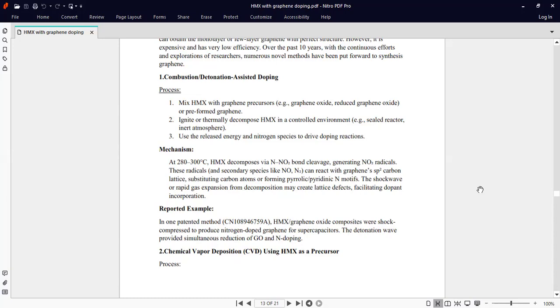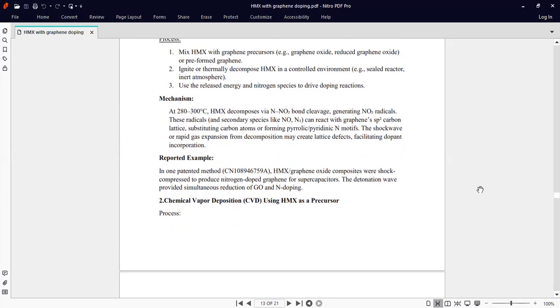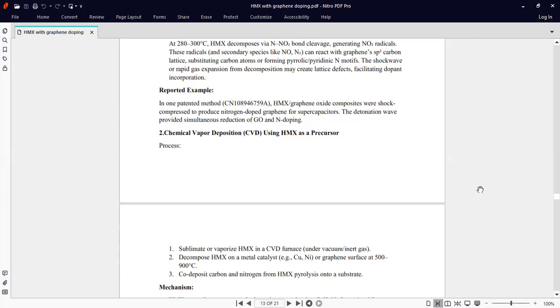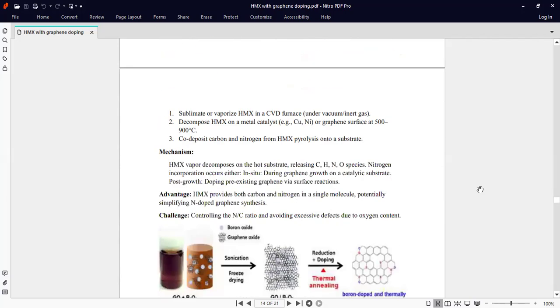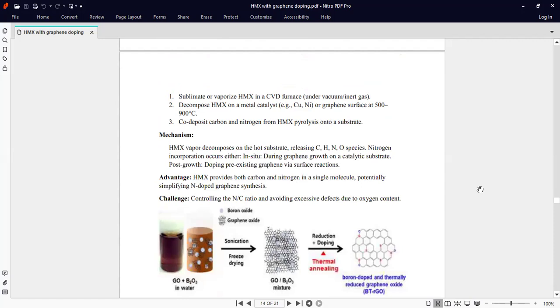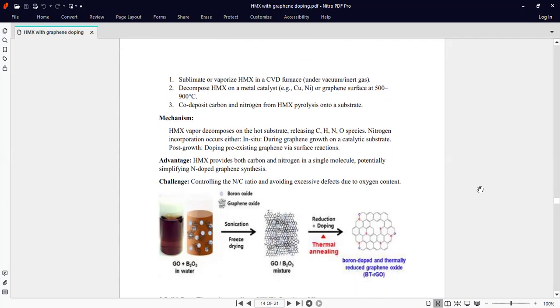Reporting an example of this type in the patent methods, HMX graphene oxide composites were shock compressed to produce nitrogen-doped graphene for supercapacitors. The detonation wave provided simultaneous reduction of GO and N doping. Next, chemical vapor deposition using HMX as a precursor. Sublimate or vaporize HMX in a CVD furnace. Decompose HMX on a metal catalyst and co-deposit carbon and nitrogen from HMX pyrolysis onto a substrate.